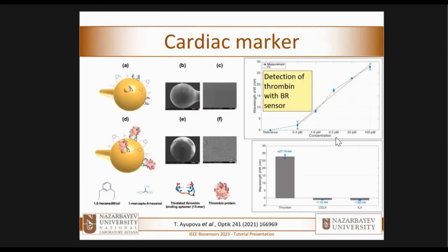So here is how a Ball resonator works in some of the biosensing applications that we have developed. The first one is the detection of a cardiac marker, thrombin, to be more specific. That's a common case for detection because it's a protein for which we have plenty of knowledge. And we have biofunctionalized the Ball resonator with a thrombin binding aptamer, so that's an aptasensor. And as the thrombin is bound on the surface of the fiber, that changes the optical spectrum. So what we have here is, in this case, we monitor a wavelength shift. Most of the time, we monitor an intensity change, and that progressively changes. So we could test basically the concentration dependence and the specificity, much like it's done on other biosensors.